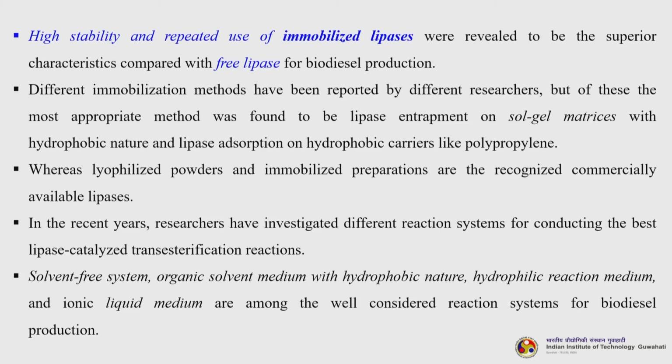So, different immobilization methods have been reported by different researchers, but of these the most appropriate method was found to be lipase entrapment on sol gel matrices with hydrophobic nature and lipase adsorption on hydrophobic carriers such as polypropylene. Whereas, lyophilized powders and immobilized preparations are the recognized commercially available lipases. In recent years, researchers have investigated different reaction systems for conducting the best lipase catalyzed transesterification reactions.